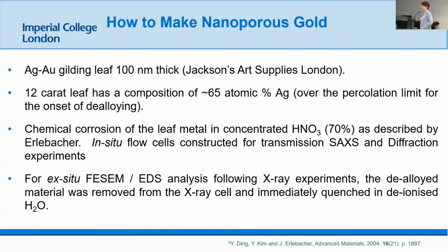How to make nanoporous gold? It's the easiest thing. You can all go home and make some nanoporous gold. You take some silver gold leaf that you might use for baking. We buy ours from Jackson's Art Supplies, but other art supplies are also available. Gold leaf is about 100 nanometers thick. It's 12 carat, which means it's 65% silver, and that's above the percolation limit. Because these are made for eating, they're pretty pure. They're not allowed to have toxic stuff in things that you can put on cakes. So it's a really nice supply of a silver gold alloy that works.